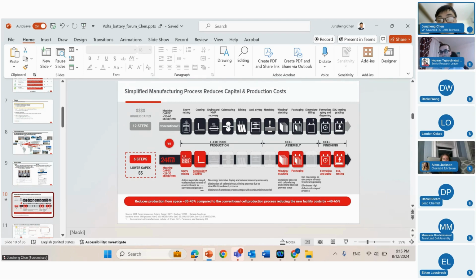And then talking about the bonding of the current collector. We have two strategies as well. First one is BET surface area of the carbon, which can absorb this active material onto the current collector. Second, there will be a van der Waals force between the liquid of this type of non-Newtonian fluid when you apply the slurry onto the collectors. So two forces form together and they can bond the current collector quite well.